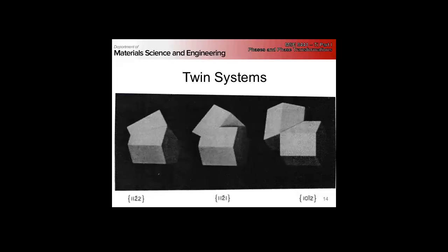If a parent grain is well oriented for twinning, say you're compressing along the C-axis, right, you've got a 90-degree reorientation. So you go from easy twin direction to easy slip direction, right, or vice versa. So we have a huge degree of anisotropy because of that. So what does that imply about the effect of texture on the properties of a finished product if it's an alpha sheet, right?